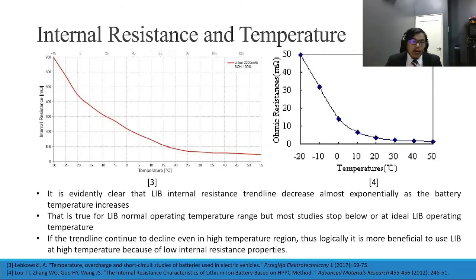That is true for the lithium-ion battery normal operating temperature range, but most studies stop at or below the ideal lithium-ion battery operating temperature. If you look at the graph, they only conducted the research until about 50 or 55 degrees. There are fewer studies that continue the temperature. If the trend line continues to decline even in the high temperature region, then logically it is more beneficial to use lithium-ion batteries at high temperature because of their low internal resistance.